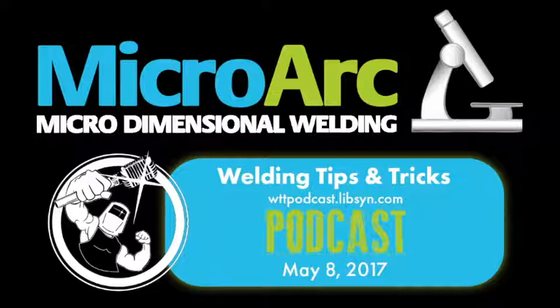Like, we'll weld high-speed steel, M2 or M42, with the TIG welding process, and it's not a problem. But once you start getting to a certain thickness, it'll start to crack every time. So it's completely different. We deal with as-welded Rockwell too. We mix and match tool steels all the time depending on hardness. If a customer says, I need such and such a Rockwell, well, the as-welded Rockwell of this type of welding wire on this type of steel isn't the Rockwell they're looking for. You know what I'm saying?